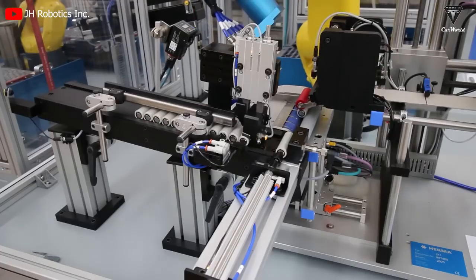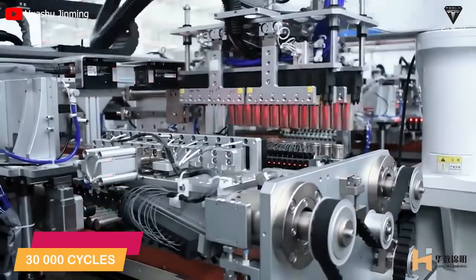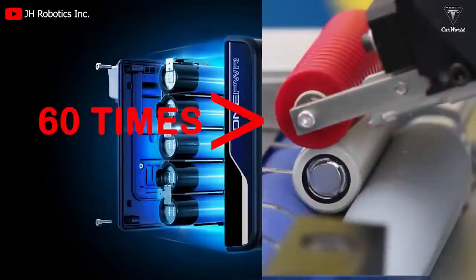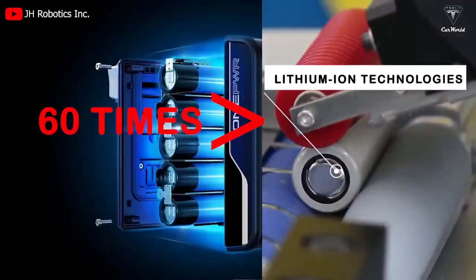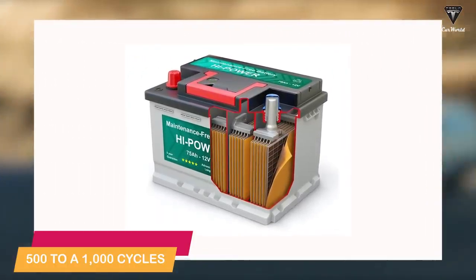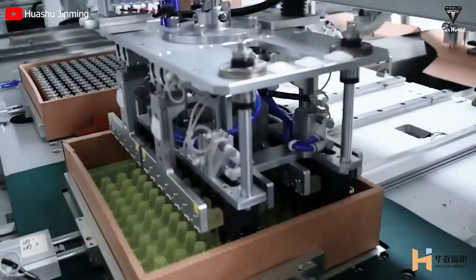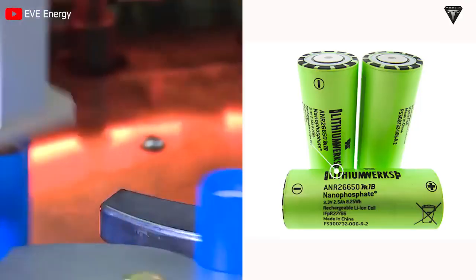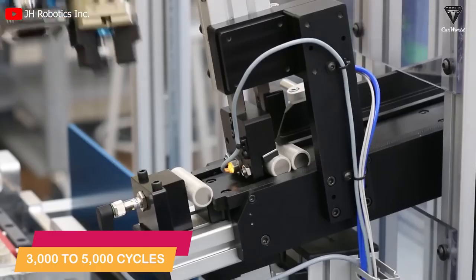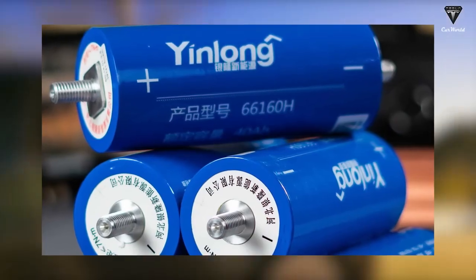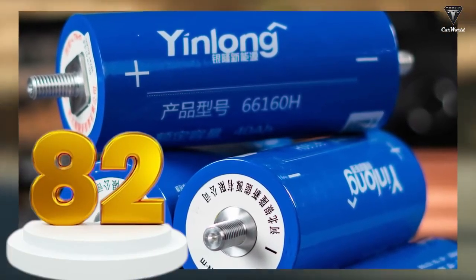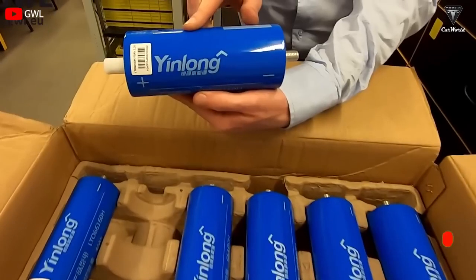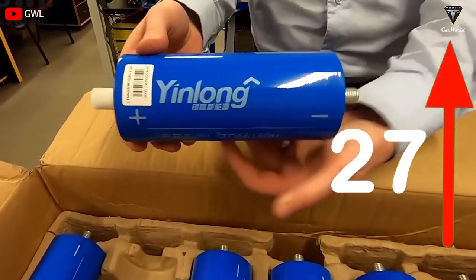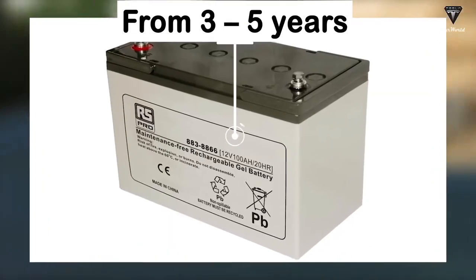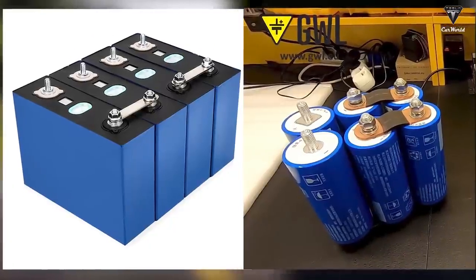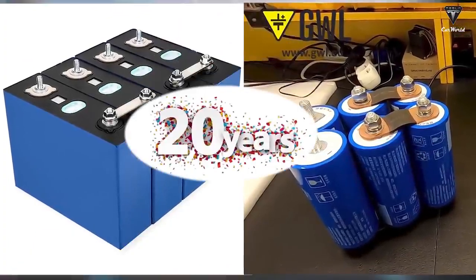The life cycle of these batteries is impressive, exceeding 30,000 cycles during cell life, which is 60 times more than competitive lithium-ion technology like lead-acid, which is 500 to 1,000 cycles. Furthermore, LTO batteries are making 10 times distance from lithium iron phosphate, and that's like 3,000 to 5,000 cycles. On the other side, the cycle life of LTO batteries gives it a lifespan up to 82 years. That's higher than 27 times of lead-acid batteries, which have a life of 3 to 5 years. And it's over 4 times higher than that of a phosphate battery with a lifespan of 20 years.